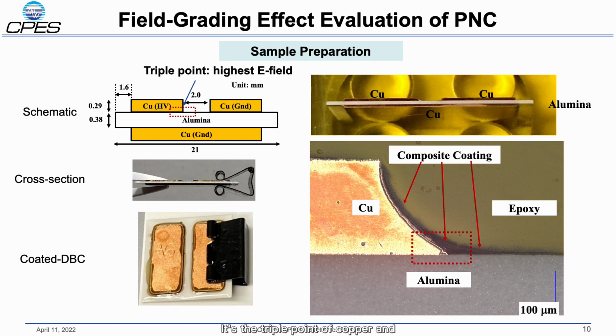It's the triple point of copper and epoxy encapsulation and alumina, which should be the highest E-field location according to the E-field simulation. Here shows the cross-section view of the real sample, and here picture shows a top view of a coated sample. To find out the field grading effect of this PNC material, we made samples with and without coating.